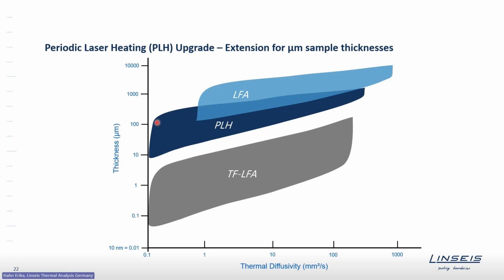Because of that, we have developed this technique in the system called PLH, which stands for periodic laser heating, and this extends the range of possibilities within the system regarding thinner materials. This is especially a useful tool for the LFA 500 series with the xenon lamp, as the xenon lamp has, on the one hand, lower energies available, and on the other hand, typically has a quite fixed pulse length. For even lower thicknesses, we have other techniques available, like the thin film laser flash, but this is discussed in more detail in another webinar.